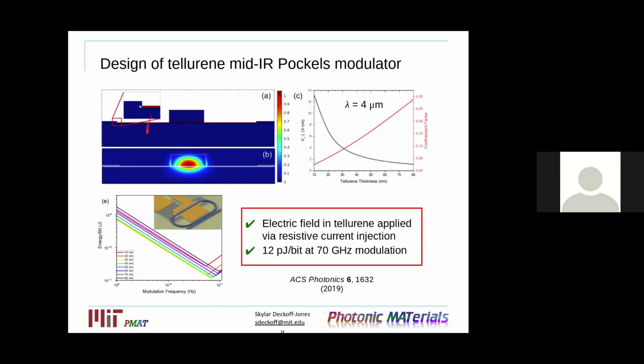So in the top left, we see the electric field in our tellurene as well as the optical mode overlap, which determines our confinement factor of our mode in our tellurene, and from which we can ultimately calculate our V pi L, which is a good figure of merit for a lot of Pockels effect-based modulators. And similarly, as you increase the tellurene thickness, you do see an increase in the confinement factor, which gives you a lower V pi L and better performance. Again, however, with the trade-off.